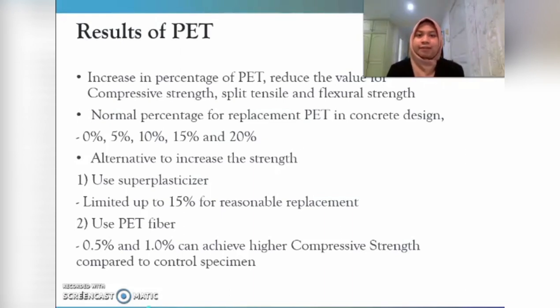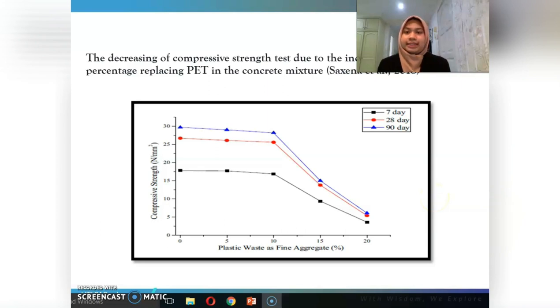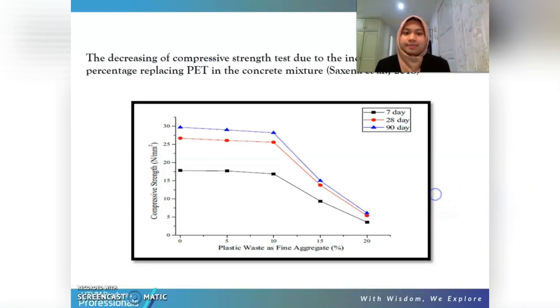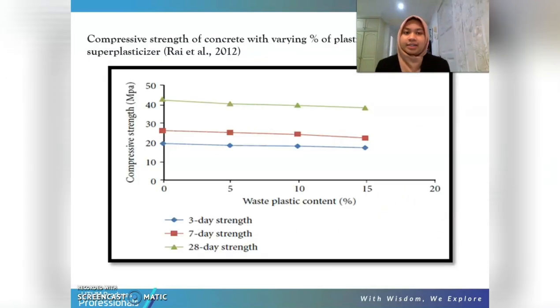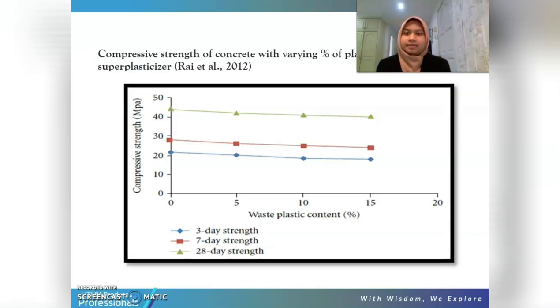Next, by using PET fiber of 0.5% and also 1.0%, it can achieve higher compressive strength compared to the control specimen, which is 0% replacement. Next, this graph shows the decrease of compressive strength due to the increase of percentage replacing PET in the concrete mixture. Next, this one shows the concrete mixture without superplasticizer. And also, this one shows the compressive strength of the concrete mixture with superplasticizer.